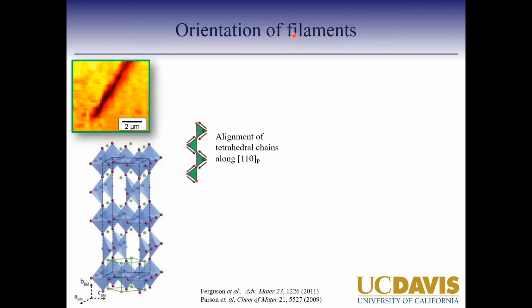And the angle specifically, thinking about that 45 to 60-degree angle for growing of these filaments, we think is related to the fact that the brownmillerite compared to the perovskite unit cell is actually at this 45-degree angle. So remember earlier I had mentioned that the oxygen vacancies order across this 110 channel, so these tetrahedrals are linked along the 110 channel, and so the unit cell is actually tilted by 45 degrees. And so that could be the reason why we are seeing this, and deviations from these alignments can happen.